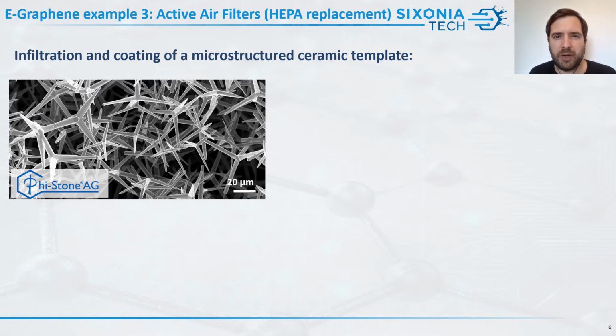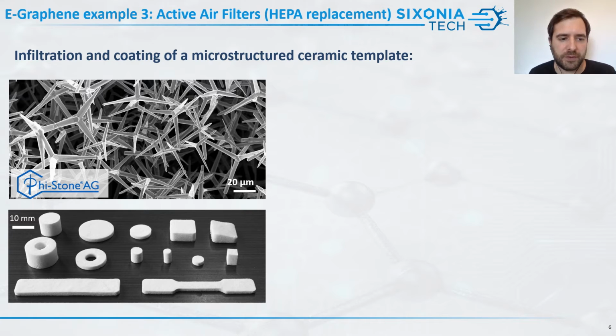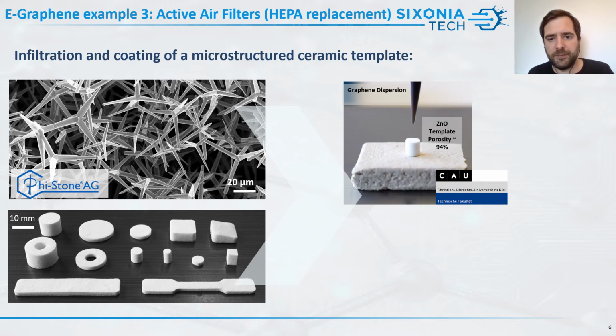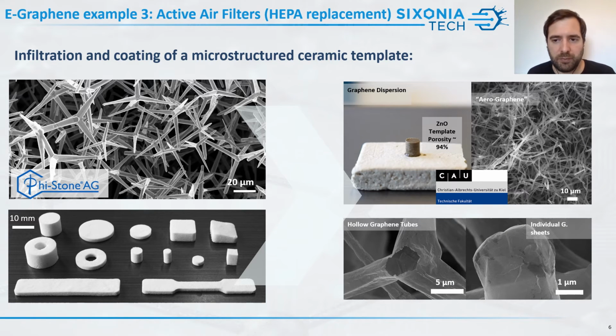The third application basically is the coating of very, very complicated surfaces. This is an example where we have a ceramic template, which is basically zinc oxide, and the graphene dispersion that we are using can be infiltrated in such molds that can be created from these ceramic particles. You can see easily in this nice video that the dispersion does not filter, there's no kind of grading effect on the surface. The well dispersed material, this aqueous dispersion in that case, is really coating this rather intricate template uniformly. You can see in these pictures that if you etch this template away, you keep this nice structure completely intact, and the graphene is really conforming very nicely to the surface of these particles.